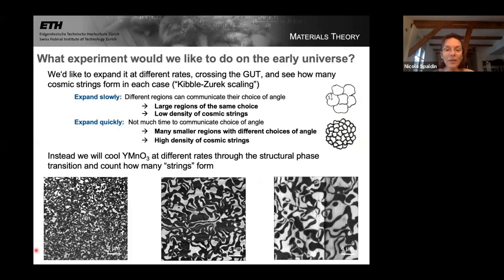These are the three most readily experimentally accessible cooling rates for yttrium manganite through the phase transition. One of them corresponds to just turning down the temperature in the furnace. One of them consisted of turning off the furnace and moving the sample to the coolest spot in the furnace. And the other was a method called drop cooling, which is a very bold experimental technique, I think, and I'll direct you to Martin Lilienblum's thesis for that one. And I should point out, this is the same scale bar in each case. I didn't just take this one and blow it up, although I could have done because it's self-similar.